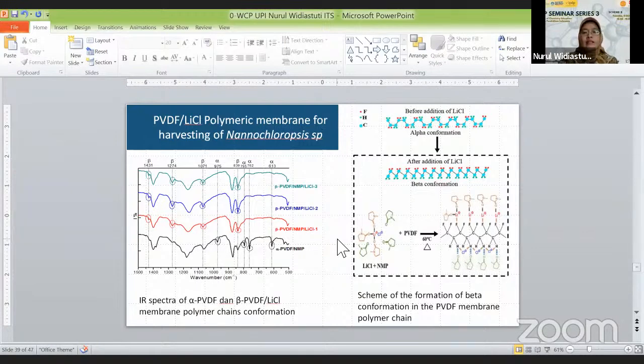And this is the illustration of why we tried to use lithium chloride in the polymeric membranes. As we see in this illustration, the lithium chloride did not chemically bind to the PVDF polymers, but the presence of lithium chloride results in a change in the structure of the polymer chains, from alpha phase to beta phase on the PVDF membranes. Then the lithium chloride will dissociate into lithium ion and chloride ion. The lithium ion as a cation will have ion-dipole interaction with the carbonyl groups in NMP as a solvent. So the lithium chloride can be completely dissolved in the NMP solvent.